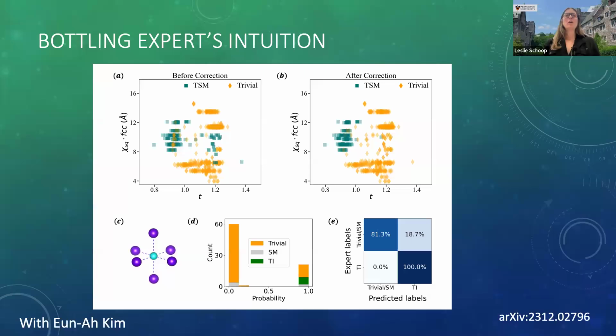So we gave it materials in the rock salt crystal structure, which is cubic, so now the distance ratio falls out because it's 1 everywhere. So our logic fails. We wouldn't know how to distinguish topological from non-topological materials with this. But we asked the algorithm what it has learned from the training set, which of these materials are topological, and it correctly predicts all the TIs that are known as rock salts to be topological with high probability. It also predicts some that are known to be trivial, so it doesn't get it completely right, but it didn't put any TI here at low probability.